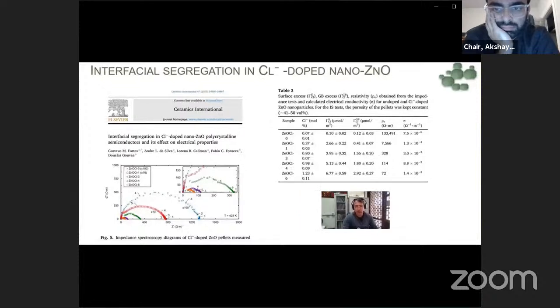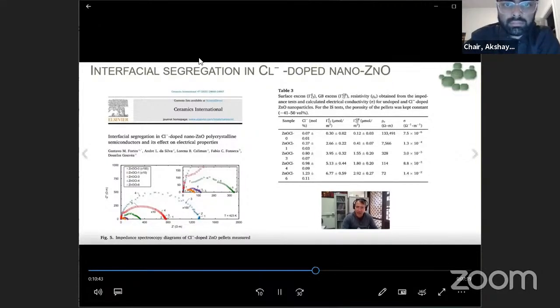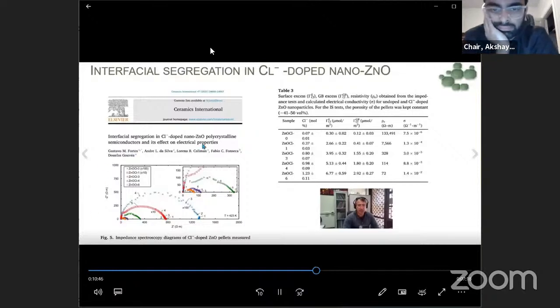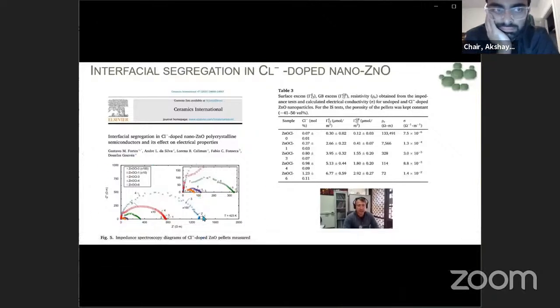The increase of total conductivity, then the conductivity of grain boundaries and bulk, increases the free pathway for electrons and holes, and then the time of recombination increases, and then you have more time for photocatalytic reactions. In this impedance spectroscopy diagram here, we can see the increase of chlorine in the zinc oxide decreases the total resistivity.